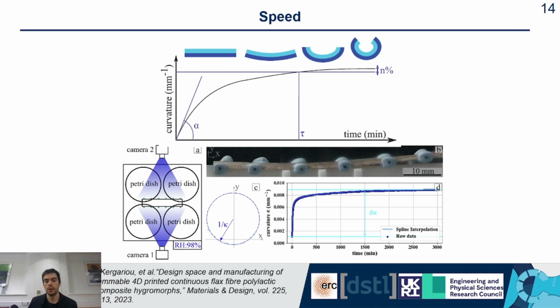So I'm going to give you an example of a kind of test. Here you have a square specimen on the left in a box. This petri dish means that there is some salt inside and water, which makes the box at 98% humidity. So the material is going to actuate. You can see you have two cameras, one on each side, and on the image you can see little trackers, basically 6 different little trackers. These trackers will be used in order to position the deformation of the material in space. Then you obtain 6 points that you correlate with a circle, and you measure the curvature from this circle. Then you plot the curvature against time, and you are able to measure the time of convergence and the reactivity, so alpha, from this curve.